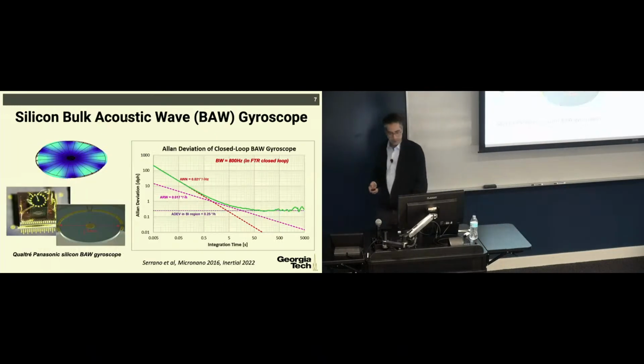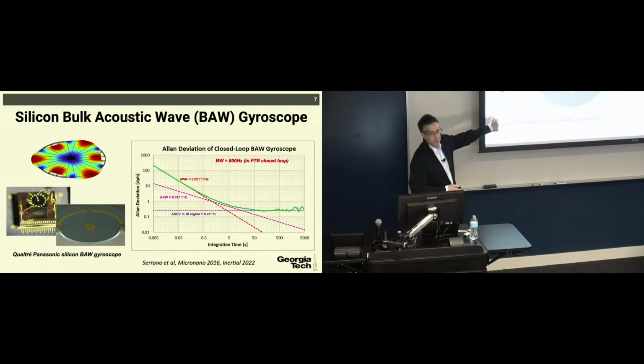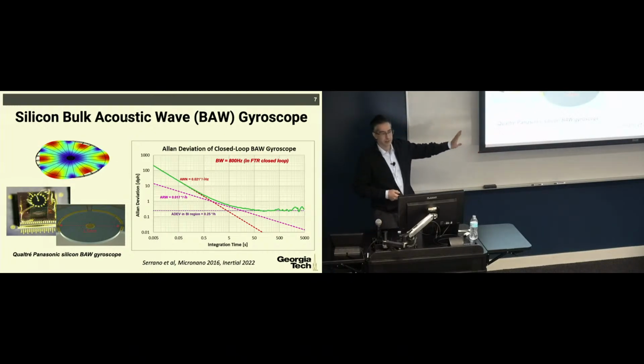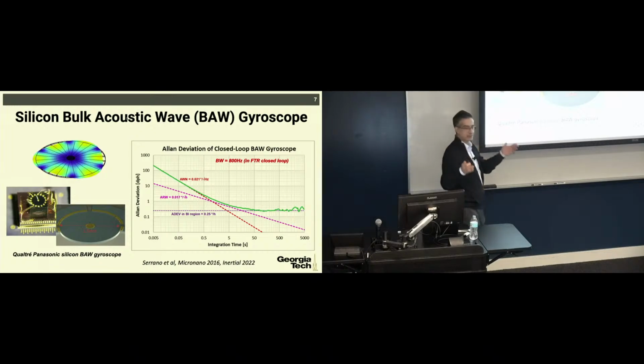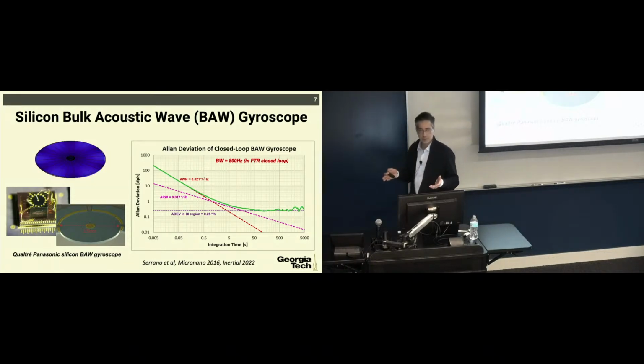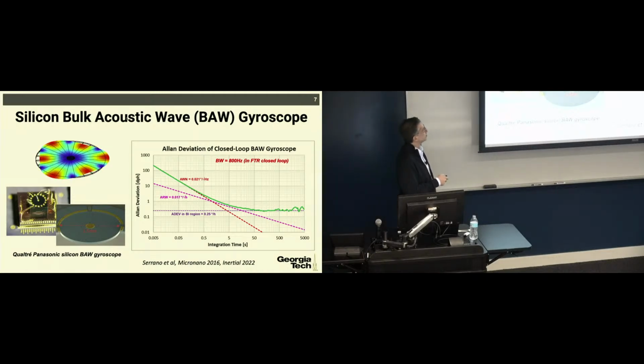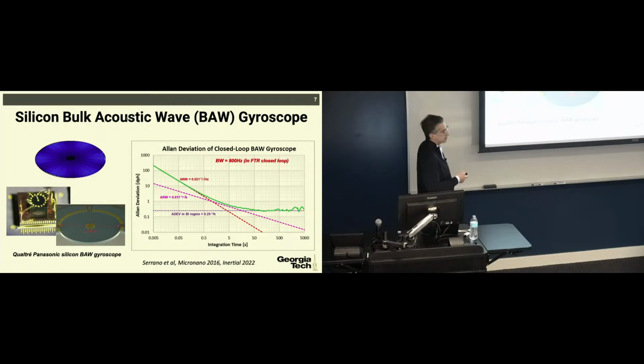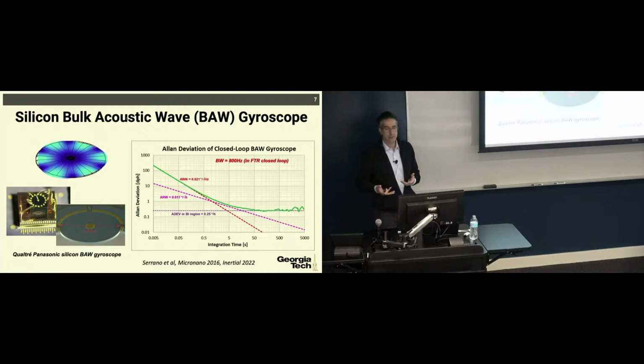And now fast forward about 12 years later, you saw that we actually make a gyroscope out of this technology. The silicon bulk acoustic wave gyroscope, again, is an electrostatic gyro that doesn't use any piezoelectric device, but uses the higher frequency bulk acoustic wave of the disk resonator. You see the picture of the disk is only 1.5 millimeter in diameter. You see it's pretty thick and is wafer level packaged through wafer bonding. So wafer bonding played a very important role in development of MEMS. And what you see underneath is the ASIC that is in charge of control and reading out of this device.